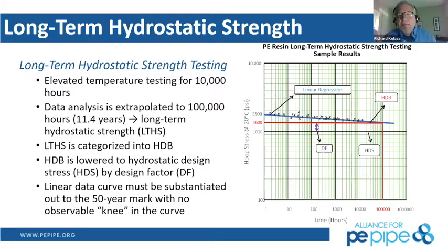But once we establish that ductility and also the hoop stress capability of the polymer and the pipe that's produced, then we can regress this line with a high degree of confidence, with a minimum LCL, which is your lower confidence limit, of 90%. So that data scatter has to be very tight like it is, and if you have one data point that's way out there, you really don't have a methodology to understand it unless maybe a poor fusion on the caps or how it was held. That's the only way you can define that or remove that point from there. Other than that, you have to go to statistical analysis to remove that data point. Next slide, please.